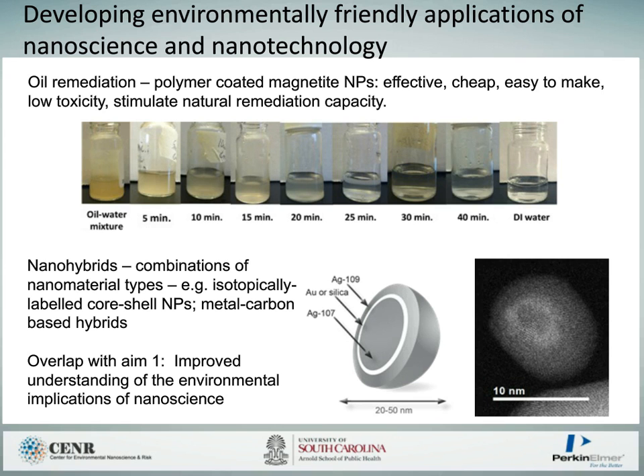And also, interestingly, we just found that they stimulate the natural remediation capacity of environmental systems, particularly the bacterial capacity of these systems. And there below you can see an example of the work we do with an oil-water mixture on the left-hand side of the image. And then as we move through various exposure times, up to about 40 minutes, we can essentially remove all of the oil from an oil-water mixture. And essentially what's happening here is that the oil, driven by the hydrophobic effect, is binding to the polymers on the magnetite. And then we can use magnets to easily separate the particles with the oil from the water, and essentially over 30 minutes to an hour remove all oil from an oil-water mixture.